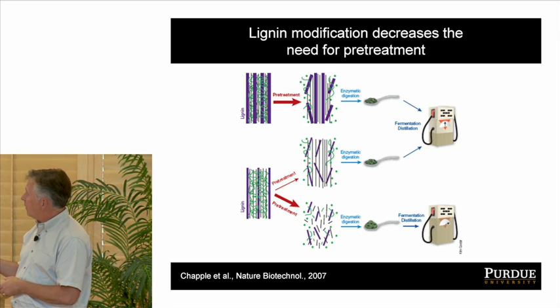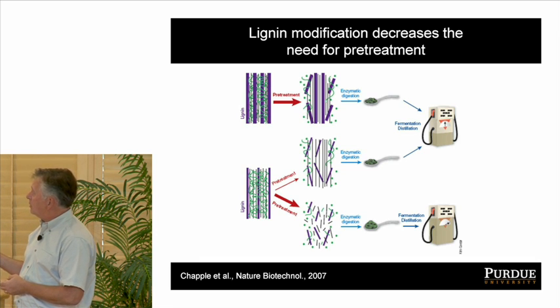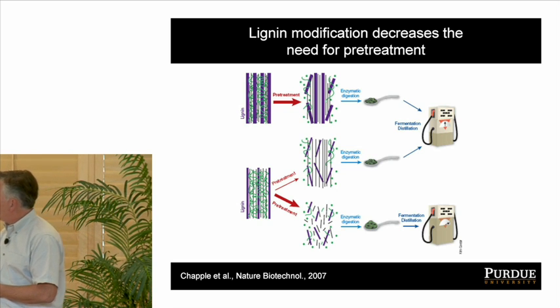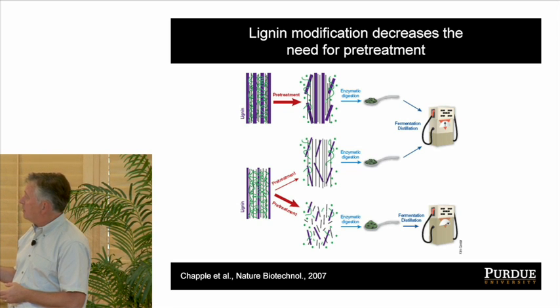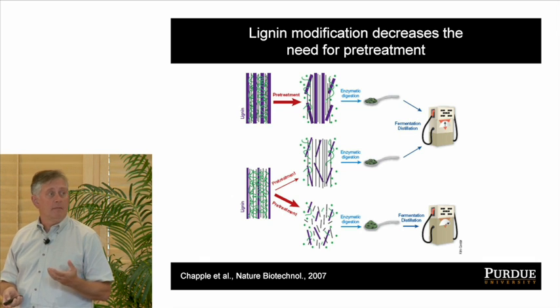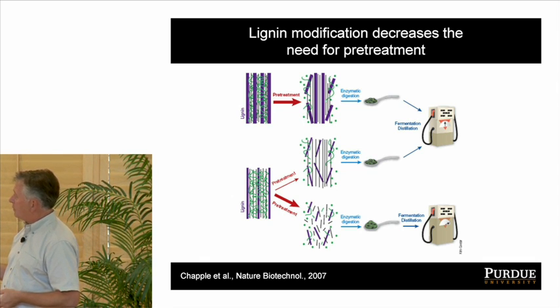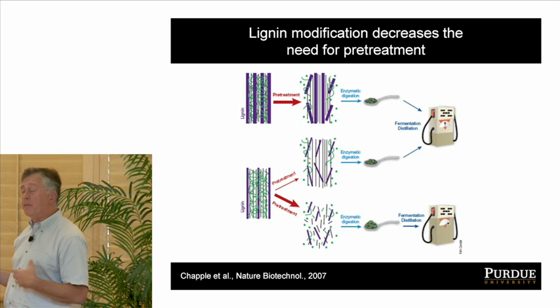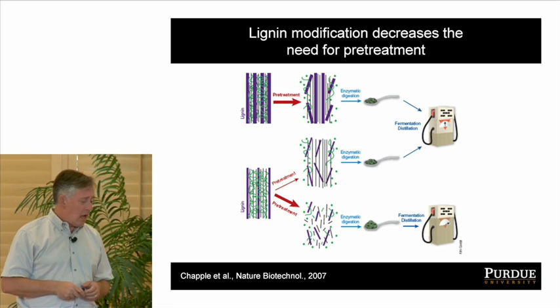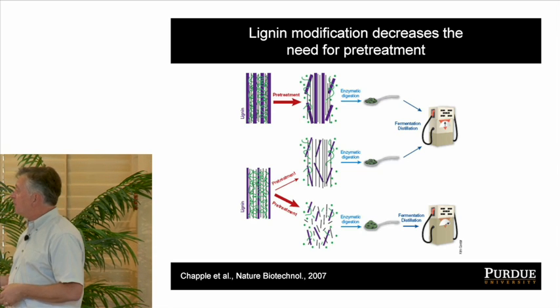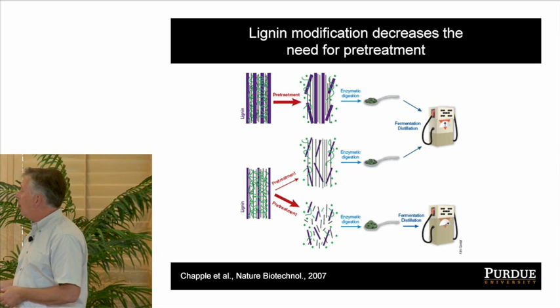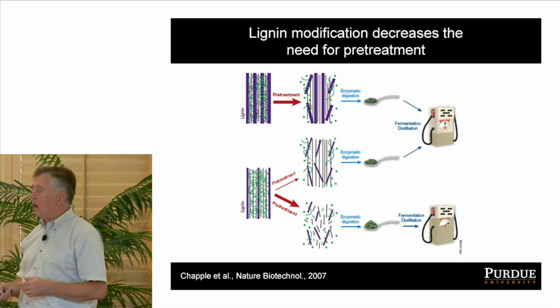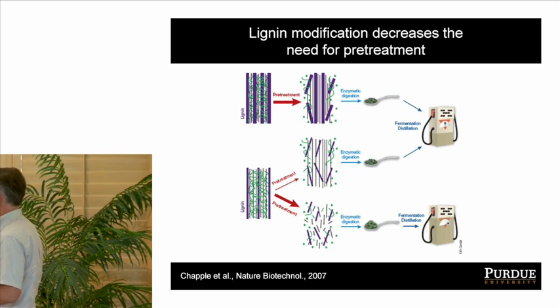And so in this diagram here, the idea is that there's a certain amount of pretreatment that you can do that will give you a certain amount of sugar that you could generate a certain amount of biofuel from. If, on the other hand, you could, for example, decrease the amount of lignin in that cell wall, so the purple bars here are thinner, standing for less lignin, you might be able to use less pretreatment and save money in that processing to get the same amount of sugars out and the same amount of fuel. Or if you found a process of pretreatment that was sufficiently inexpensive, perhaps you could have a more thorough pretreatment, blow that cell wall apart, and get even higher yields of both fermentable sugars and fuels.